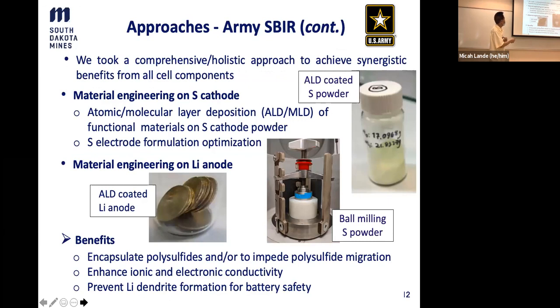So what we came up with is a holistic approach to achieve synergistic benefit from all the cell components, not just one. First, the sulfur cathode. One of the approaches is we coat the sulfur with atomic layer or molecular layer deposition, ALD and MLD, materials. So here is the coated material. You can see the sulfur powder is in there. Another approach is just to optimize the formulation, and one of the tools we use is a ball mill to achieve that purpose.